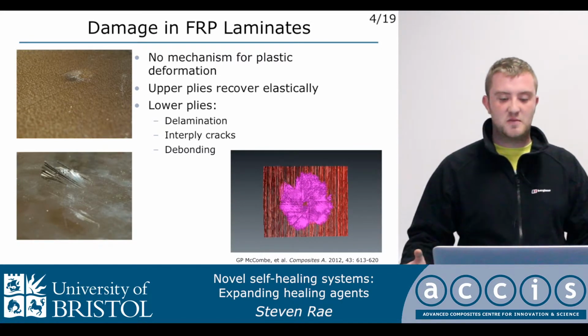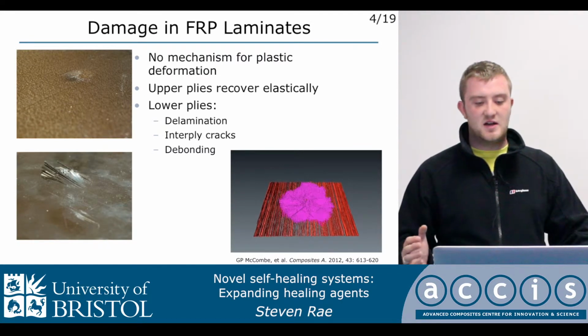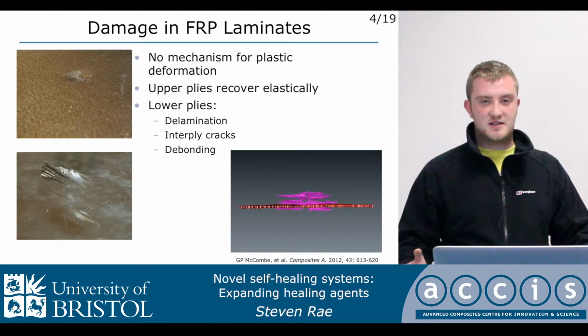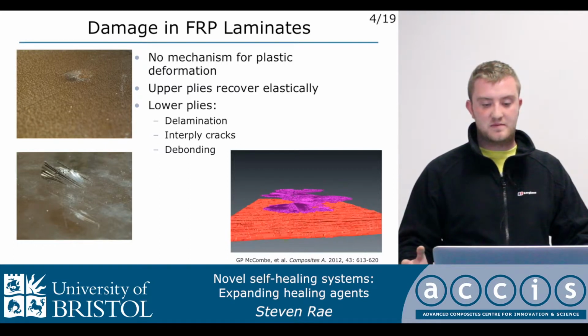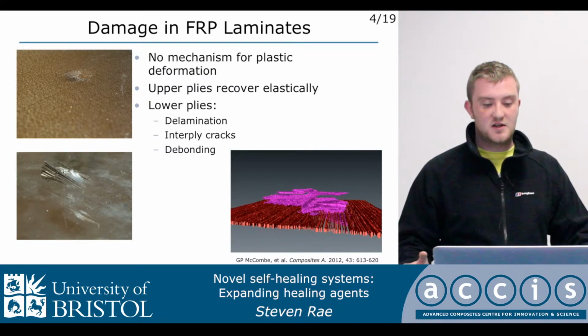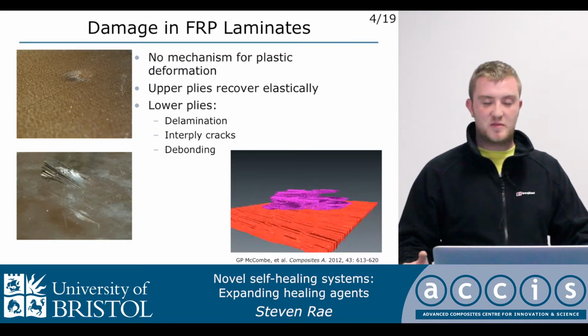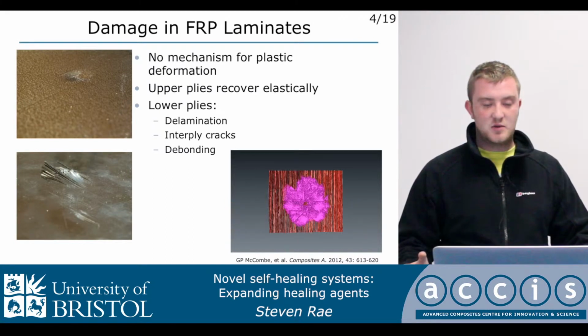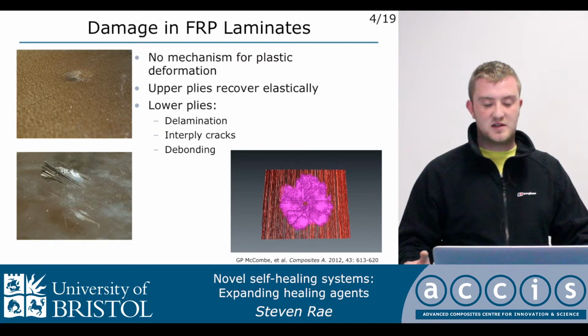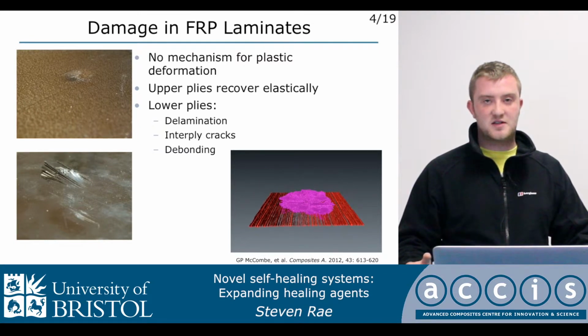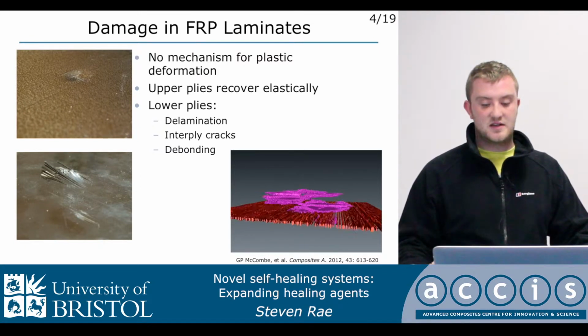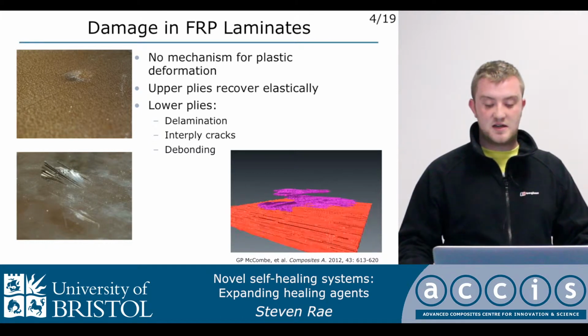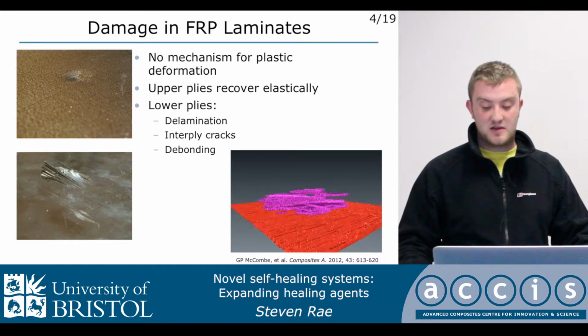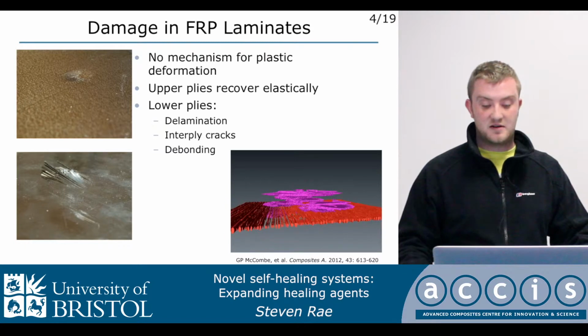This lack of trust in composites comes from the fact that composites are almost completely elastic to failure. There's no plastic deformation mechanism. So in an impact event, often the upper plies will recover elastically, whereas in the inner plies there will be delamination, crack formation and debonding between the fibres in the matrix. As you can see from this CT scan here of an impact on a composite plate, there can be a significant damage volume internally.